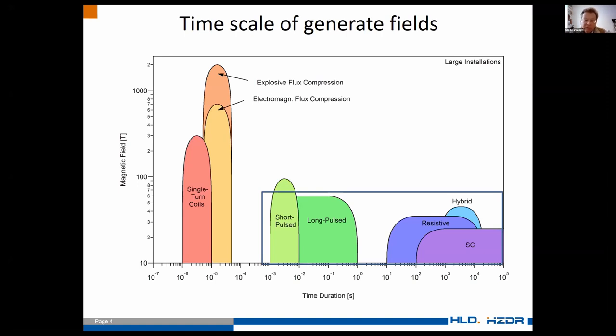And for an even higher field range, we should use single-turn coils. You can see here that the pulse duration is about several microseconds, compared to the short pulses I just showed you, which have a duration of about several hundred milliseconds. Here we have several microseconds, and we can talk about different techniques. But to get really very high fields, you have to go to flux compression. It can be electromagnetic, which is approximately up to 650 Tesla, and for about 2,000 Tesla, you have to use explosive flux compression. As far as I know, the record is 2.8 kilotesla, which was done somewhere in Russia.